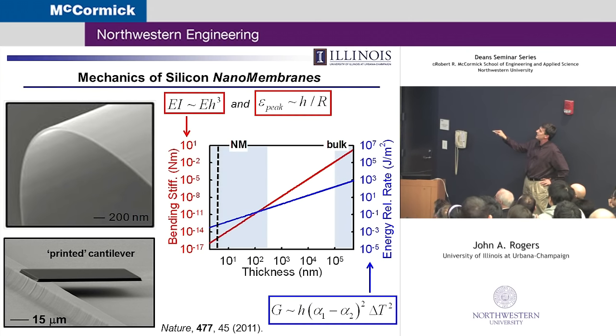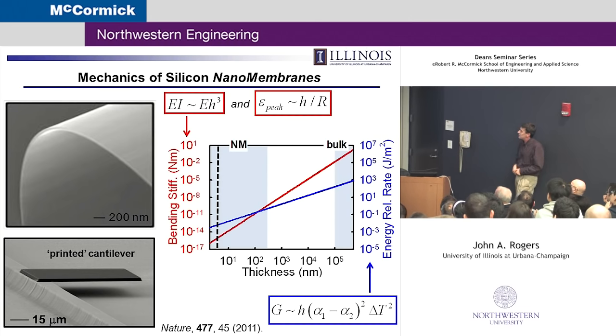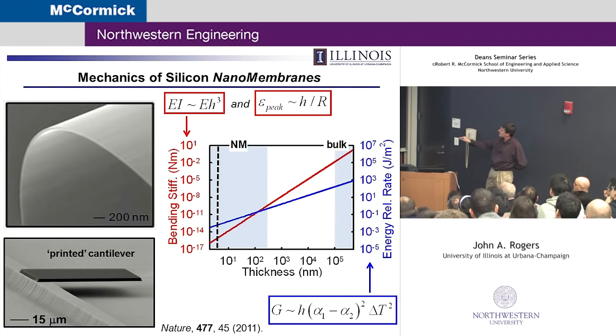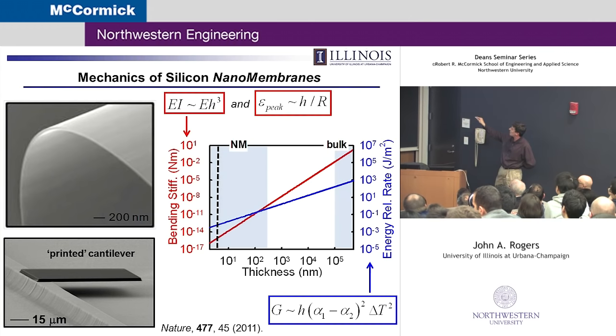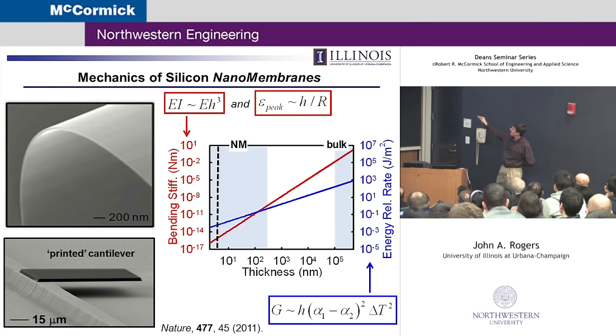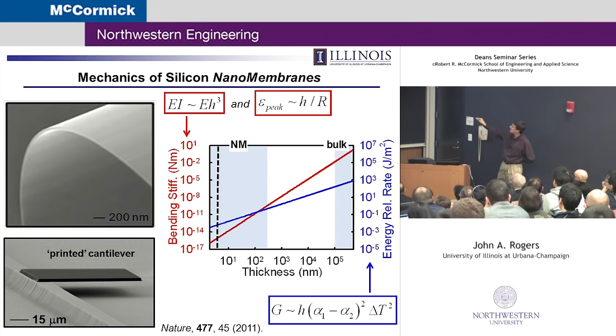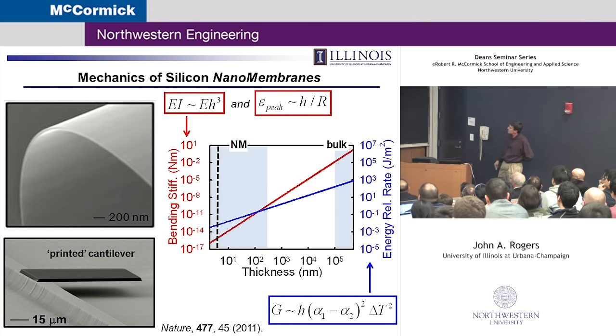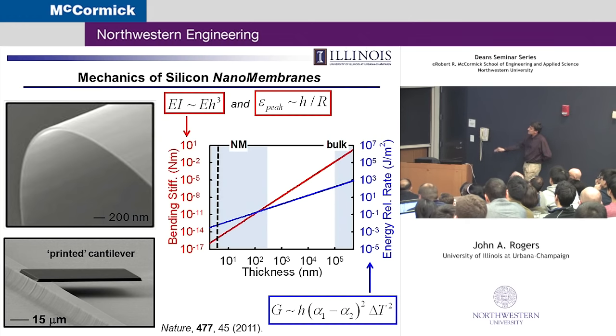So that means not only making the silicon thin has these appealing attributes in intrinsic mechanics, but it makes it much easier to do heterogeneous integration because this energy release rate is scaling down linearly with thickness. So again, you go from a wafer scale system, very, very difficult to maintain adhesion, to a nanomembrane configuration with a stick without any adhesive at all.